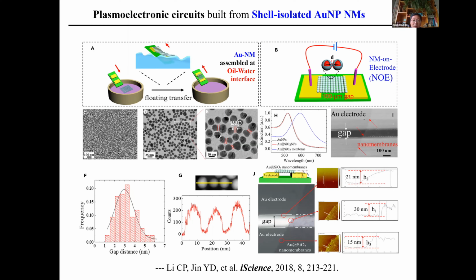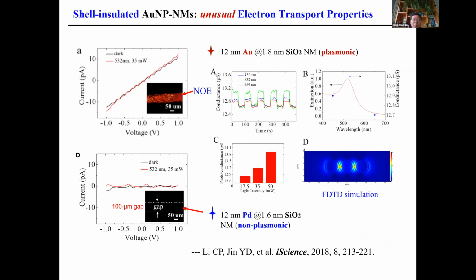The robust nanomembrane can be transferred to cover the two charge electrodes. The nanoparticles have been well separated by the silica gap, and the gap can be tuned by the thickness of the shell. Very interesting. Today, in a typical junction made of 12 nanometer gold with a 1.8 nanometer silica nanomembrane, we observed an almost linear response in IVs, but an obvious step-like feature, which is a signature of nonlinear electron tunneling.